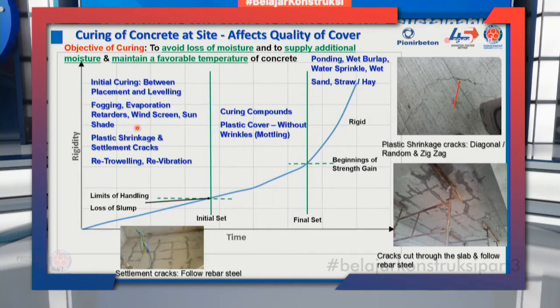I did not tell something on this type of cracks. If the plastic shrinkage crack is there, it is always zigzag, very zigzag. And this has become wider because someone has walked on it, the crack tip has broken. And the plastic shrinkage cracks are deep enough. They can cut through the slab. You can see here, this is the bottom of the slab. You can see all the lines here, water leakage. The lines are along the rebar. So if you wash your car on the upper deck, the water will fall on the lower deck. Same thing happens in a toilet also.